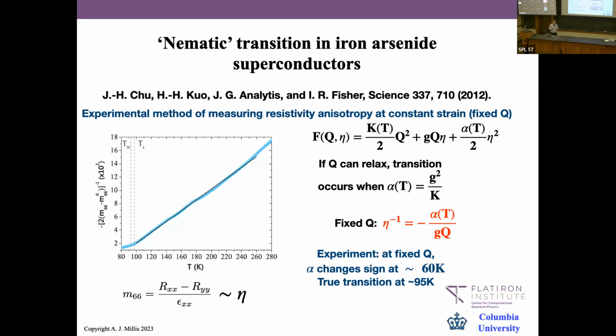And this was an important result, because there was years of controversy about whether there can be an electronically driven C4 to C2 symmetry breaking. And then Leonid had raised the question of what happens here. To my knowledge, nobody has extended the free energy analysis into the ordered state to make sharp statements here. But basically, you would add quartic terms here, particularly in the electronic interaction, and then there's a fairly obvious set of things you could do.